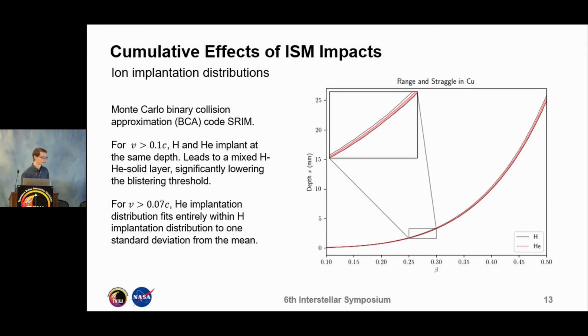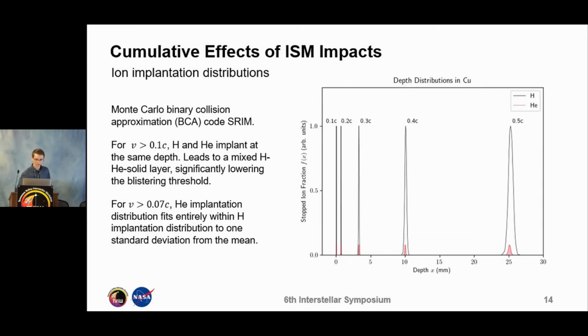And for velocities greater than 7% of the speed of light, the helium implantation distribution fits entirely within the hydrogen implantation distribution, as shown here. So this is a plot of the implantation depth for different speeds, and you can see it's just normalized to 1 so that we can show what it looks like on the same scale.